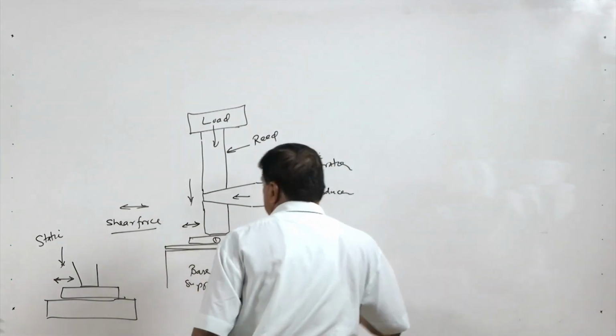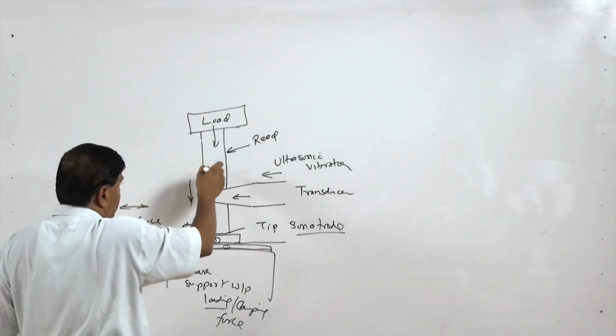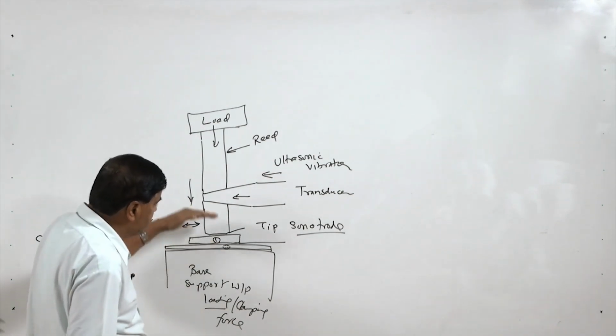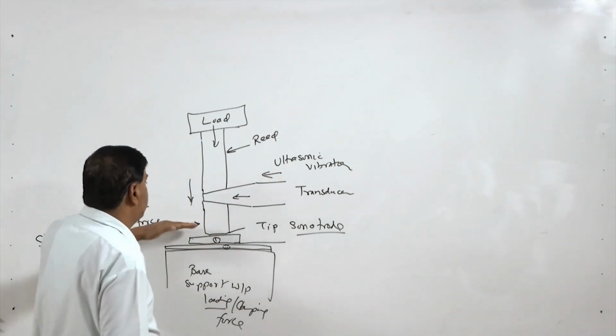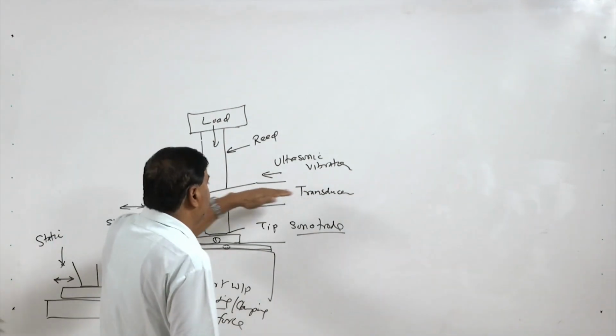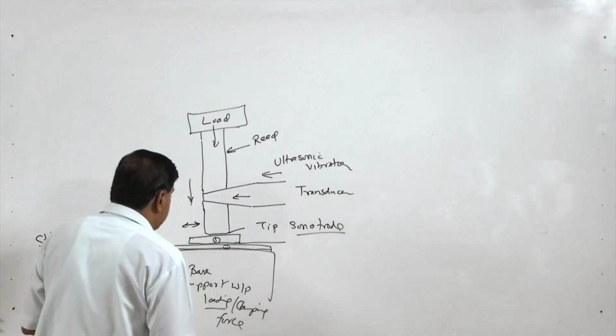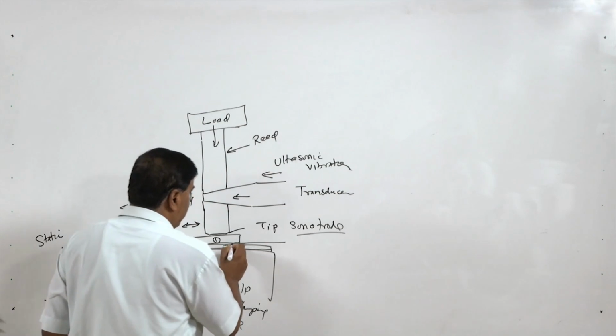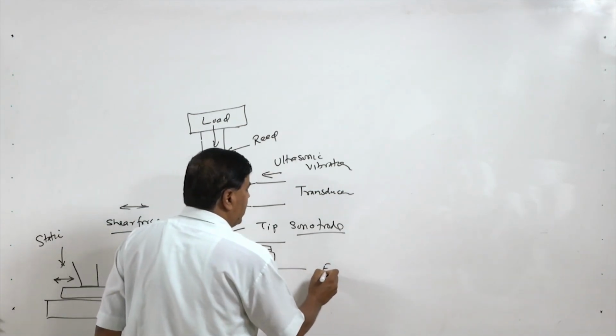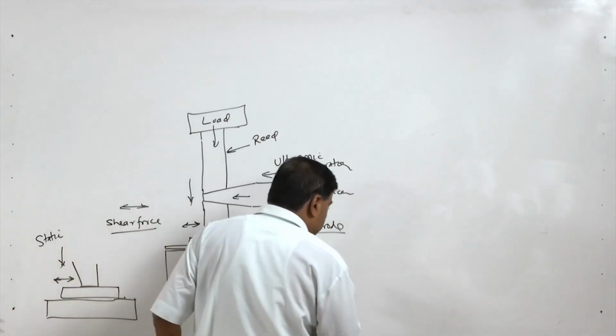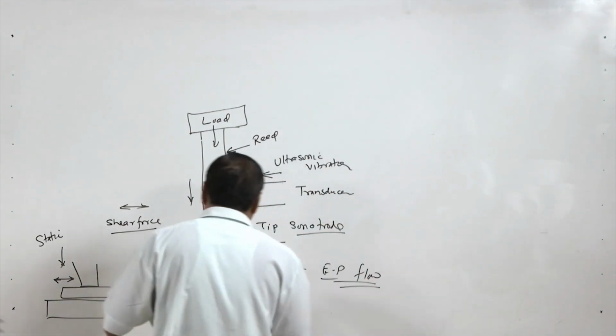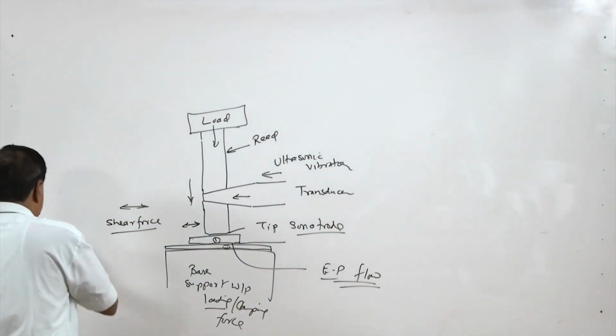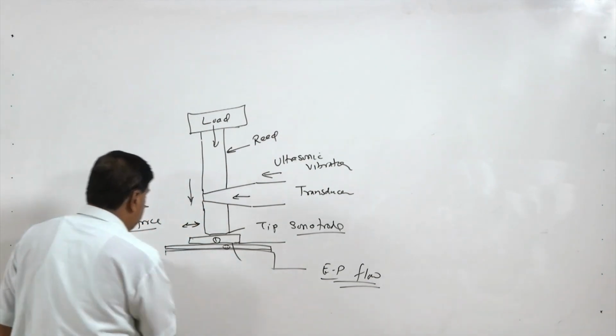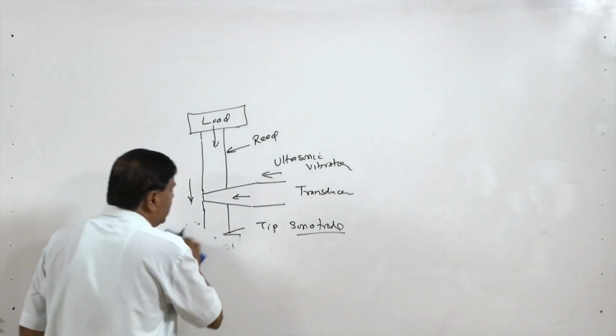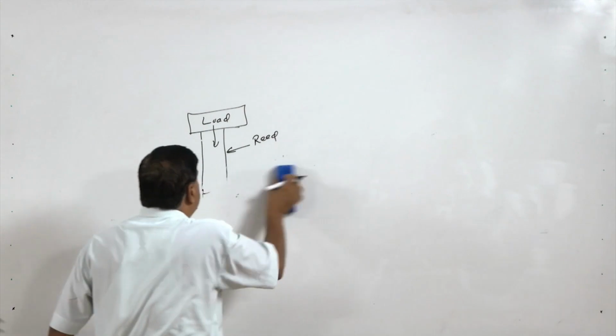So, in this case what we have seen, we are applying the static load which will be basically holding the workpieces to be joined, and then lateral shear force which will be applied in the form of vibratory energy through the transducers. This combination of the two facilitates very dynamic conditions at the interface, and facilitates the elastic plastic flow of the material at the interface, and that in turn helps in development of the joint at the interface.